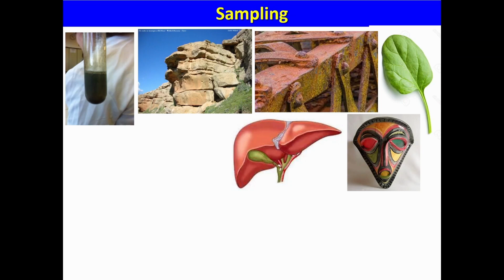Okay, so now the second point, the sampling. Sampling appears to be a very easy problem, but it's not. Of course, when you are working with a chemist, I have done this, you can estimate very easily the quantity of sample to put in your sample holder. But when you are working with, for example, rocks, it's quite difficult. It's also quite difficult because you are looking to identify the different phases. I remember I did something similar with a colleague from geology. I need 5 milligrams of iron per square centimeter, so large eyes, but I am working on several tons.